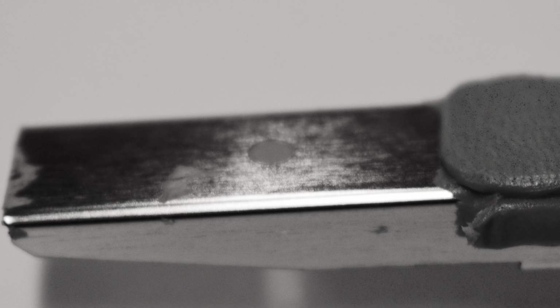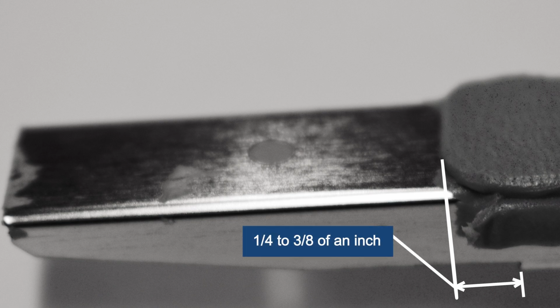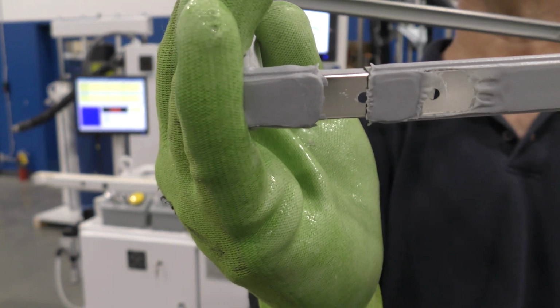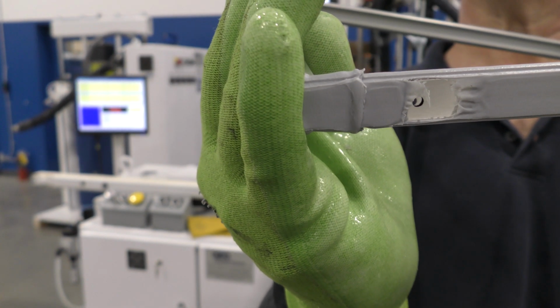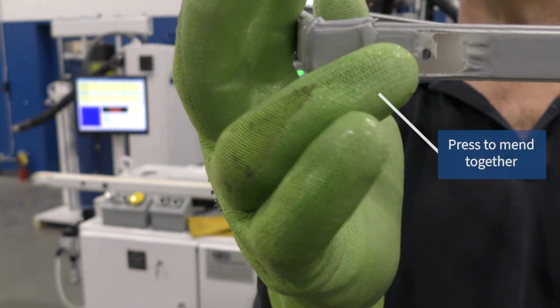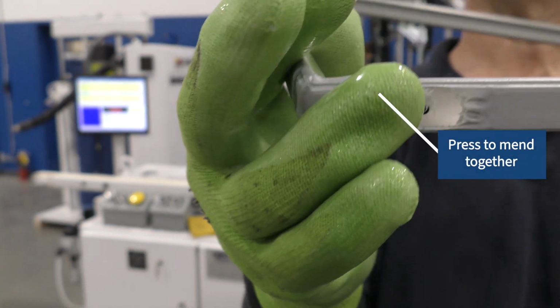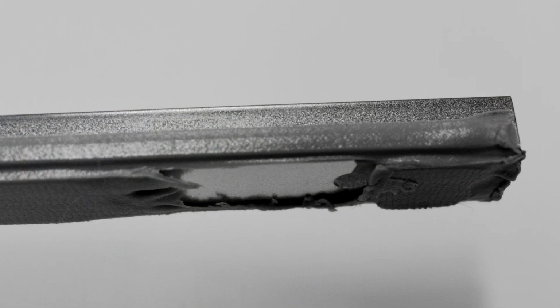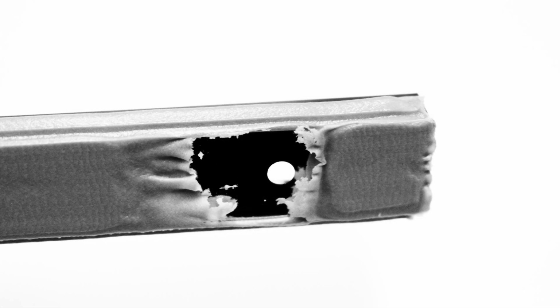The sealant applied to the bottom and side of the spacer must start prior to the end of the tab by about 1/4 to 3/8 of an inch. This sealant material on the tab is tucked into the fourth corner during assembly, which provides sufficient sealant material needed to mend and seal the corner after the tab insertion. The extruder operator should examine the spacer end to verify the sealant application. Side sealant must continue all the way to the end of the spacer. The last portion of the bottom sealant is needed to support the mended joint.